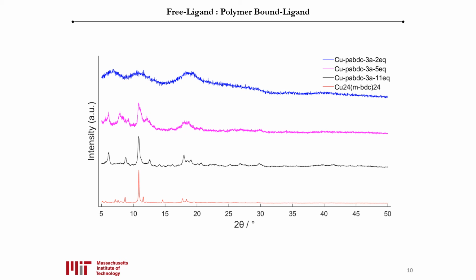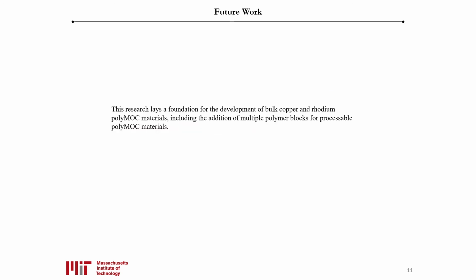After the reactions were completed, a powder X-ray diffraction, or PXRD, was taken of the ending material, and it indicated that increasing the amount of polymer disrupts the crystallinity within the metal organic cages. This research then lays the foundation for the development of bulk copper and rhodium poly-MOC materials.